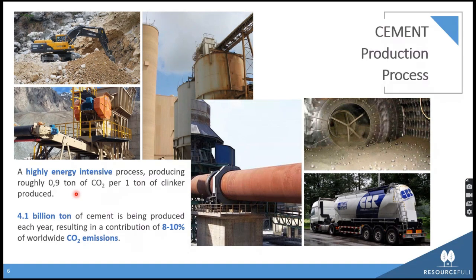If you make steel, it's more like 2.5 tons of CO2 per ton of steel, and primary aluminium, for example, can be up to 15. So ton per ton, cement is already on the low side. And then we don't even talk about concrete, where we use so little cement per cubic meter. But because of the production volume of 4 billion tons per year, and that's going to rise towards 5 or 6 billion tons per year by the year 2050, the material is responsible for 8 to 10% of the worldwide CO2 emissions.